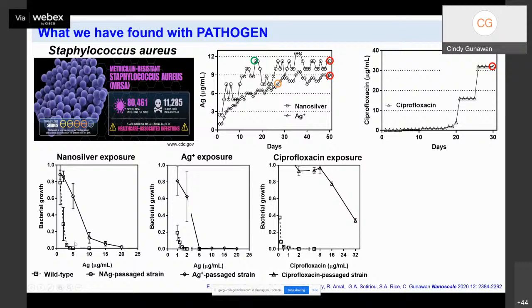And as you can see, the minimum inhibition concentration of nanosilver on the wild-type strain is about 3 micrograms per mil. So minimum inhibition concentration is the smallest concentration of an antibacterial agent to inhibit the growth. And here for silver nanoparticles, we could see that the MIC is at 3 micrograms per mil for the wild type.